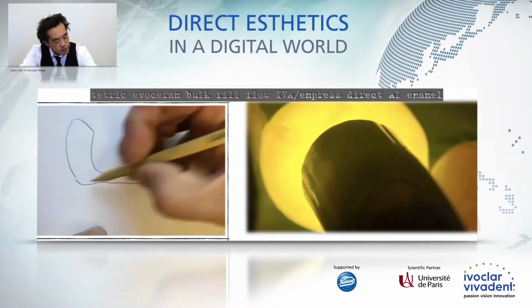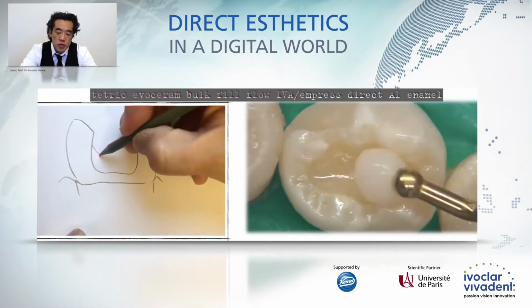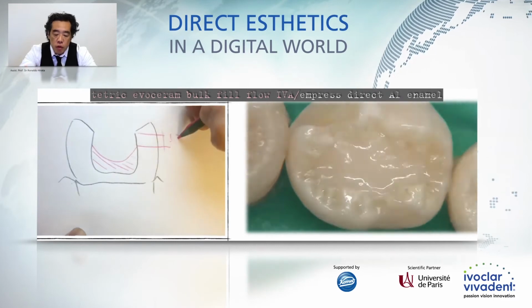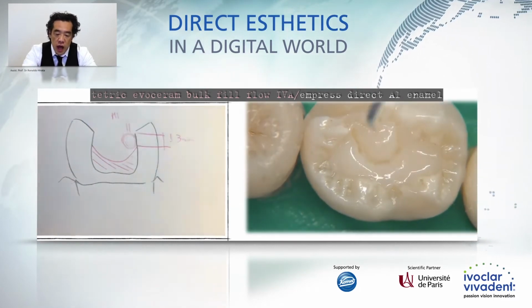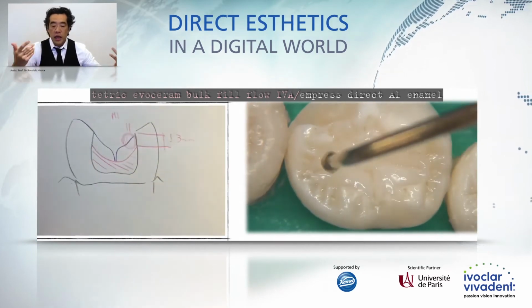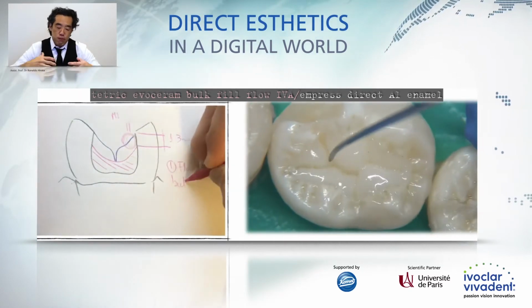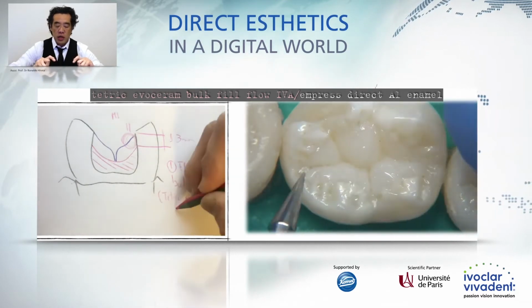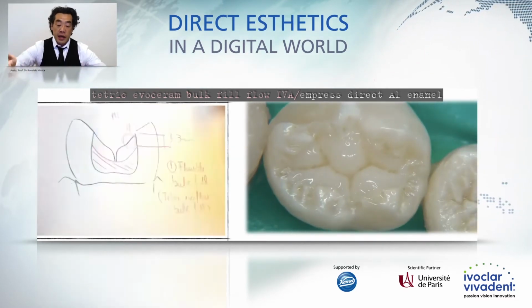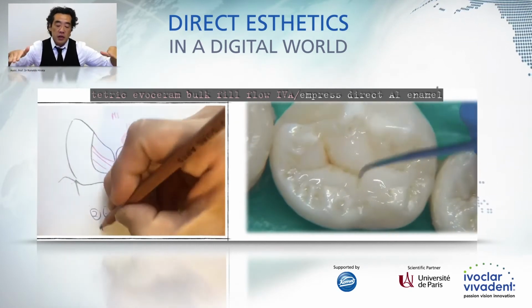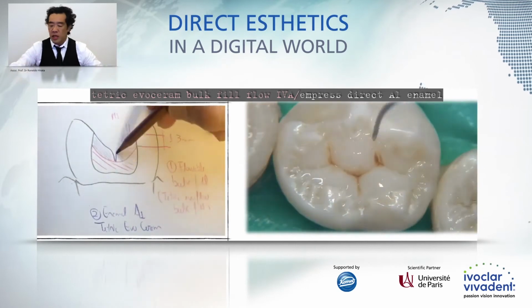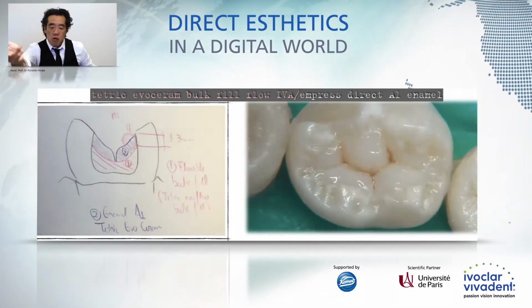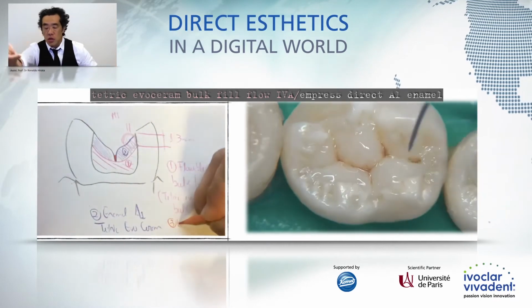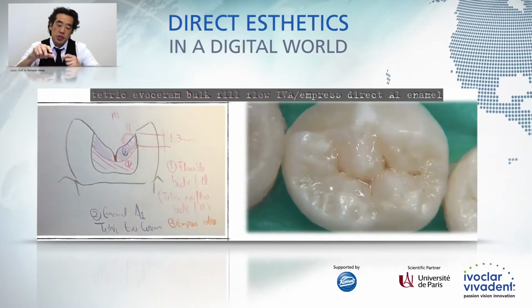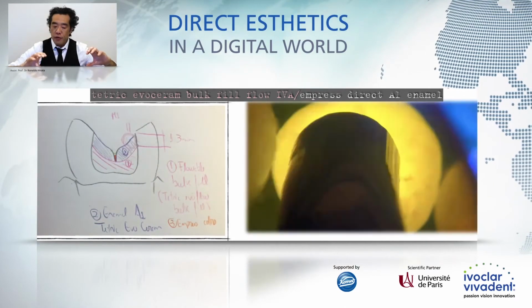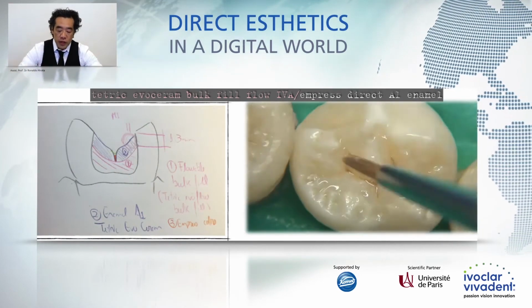I'm going to show you in this video, a very quick video, just showing you the flowable Tetric EvoCeram Bulk Fill. The shade used was IVA, that is kind of universal, the A shade. I just bulk fill. I can use a layer up to 4 millimeter thickness, and I can cure in just one time. I just leave a space for a covering composite. That can be a regular composite like Empress Direct or Evoceram or Tetric Prime. I just finish the restoration in 2 layers. I bulk fill everything with this flowable composite, and then I cover with another one.